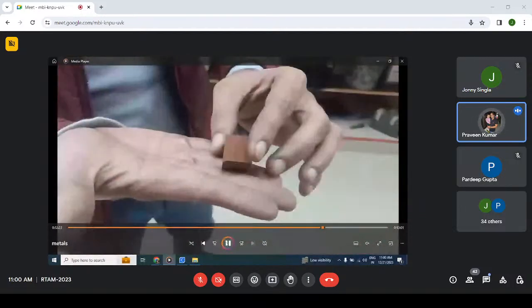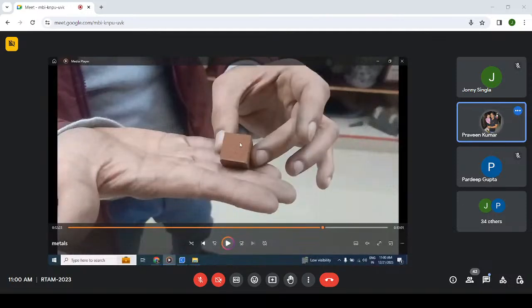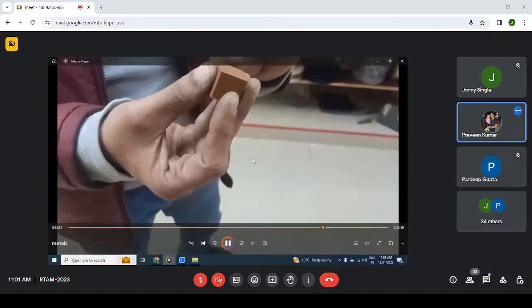Now I have removed this material from the build plate. Here you can see this material is 3D printed, and it has 83% metal and 17% PLA polymer as adhesive. So this part is not strong enough, so we need to remove the polymer part. For removing the polymer part, we need to do sintering. So we will just start the sintering process.